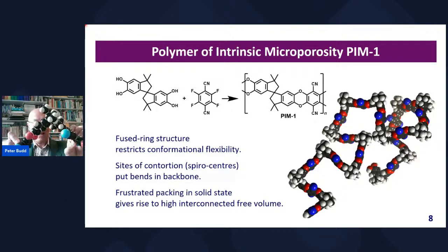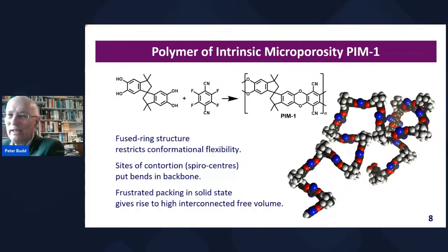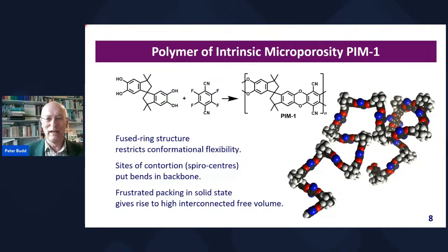And if we have a lot of these bends, we end up with a polymer that twists and turns a bit like a normal polymer, but because of the fused ring structure, it can't change its conformation in the same way. So these spirocenters, which are examples of what we call sites of contortion, put bends in the backbone, but now we have something which can't pack effectively, and we end up with high free volume. We end up with something which is like a microporous material in the sense in which I've described it,